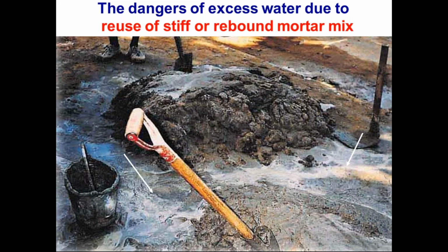So the entire water to cement ratio goes for a toss. And it may even exceed 0.8, 0.9, or it may even become 1. In concrete or in plaster, if the water cement ratio is very high, durability will be lost and cracks will be formed, and therefore you will lose the purpose of the plaster completely. If you are not careful, you must restrict the worker not to use such a plaster because of the high water cement ratio. It's very, very important.